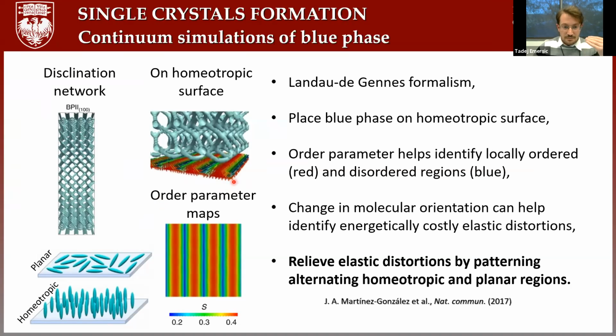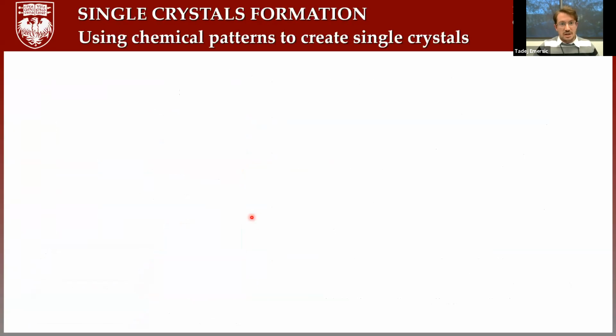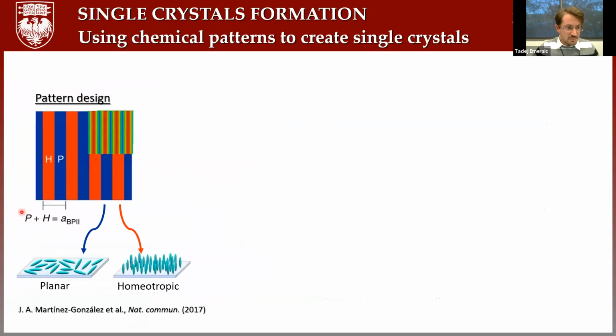So that means that the system prefers that on the surface, we have alternating regions between homeotropic anchoring and planar anchoring. So in other words, from simulations, we can map the order parameter. The order parameter tells us how the liquid crystal molecules are ordered, right? Such an order parameter map actually provides a blueprint for creating patterns of planar and homeotropic regions whose aim is to relieve the elastic distortion induced by the surface. And so, according to simulations, we made patterns in experiments.